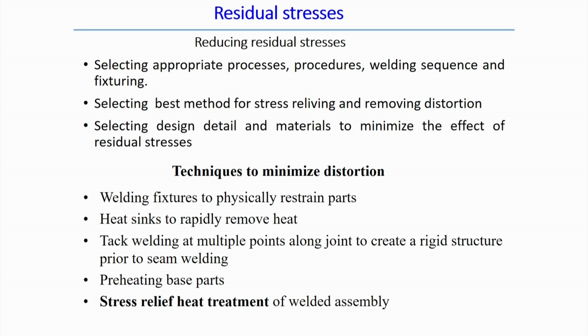Tack welding at multiple points along the joint creates a rigid structure before the seam welding, which actually minimizes the distortion. Preheating the base part, and finally stress relief by heat treatment of the weld assembly, is the most general method to reduce the amount of distortion and residual stress. Now, we will look at some distortion field simulations in the microplasma welding